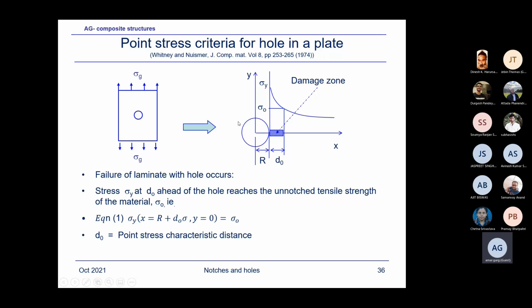shown over here. What we say from the point stress criteria is that there is some damage zone around the hole edge, and the failure would occur when at this distance, which we call the characteristic distance, the stress is equivalent to the unnotched failure strength. Sigma naught is the laminate failure strength without hole or notch. So failure of a laminate with a hole occurs when the stress sigma y at d naught ahead of the hole reaches the unnotched tensile strength of the material, sigma naught. That is sigma y at x equal to r plus d naught.